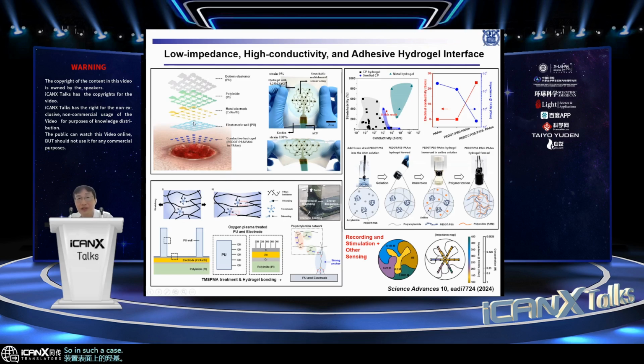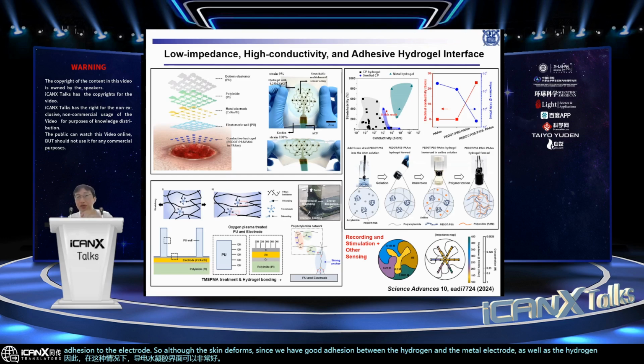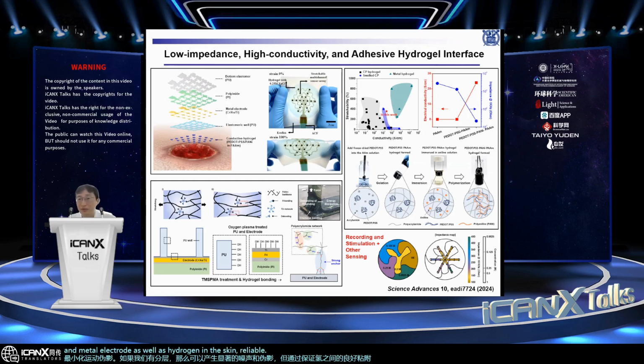So in such a case, the conductive hydrogel interface could make very good adhesion to the electrode. So although the skin deforms, since we have good adhesion between the hydrogel and the metal electrode, as well as the hydrogel and the target skin tissue, a reliable signal can be achieved. And that is also very important to minimize the motion artifact. If we have delamination, then significant noise and artifacts can be made. But by guaranteeing good adhesion between the hydrogel and metal electrode, as well as hydrogel and the skin, much more reliable sensing could be achieved.